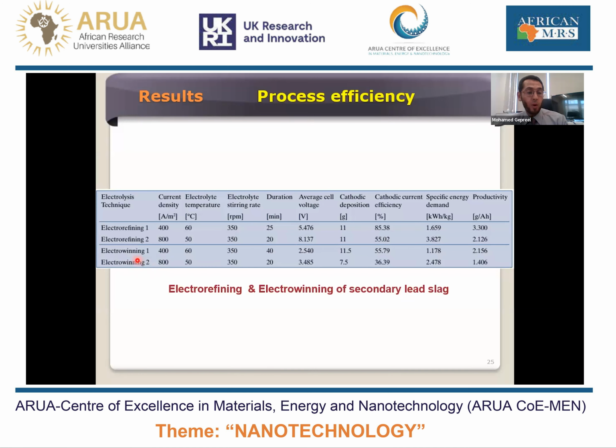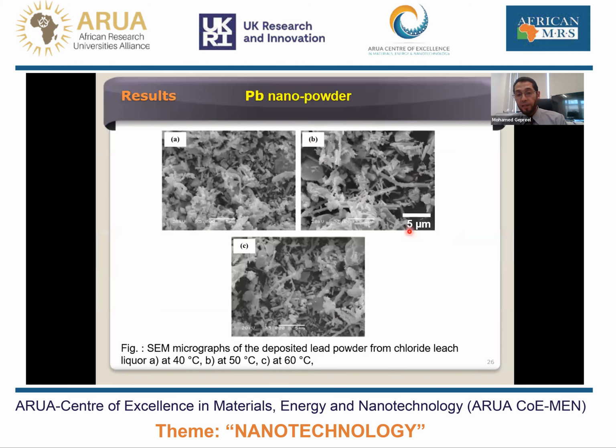Actually, electrowinning is a one-step process and electrorefining is a two-step process, which means cost. But at the end, the efficiency of the one-step process is less than that of the two-step process, so this should be optimized. At the end, we have fine lead powders, as we can see here. This is one of the selected conditions showing the effect of temperature on lead powder production. We can also see an irregular shape of lead particles. We can have rods, nanorods, fine powders, chunks, agglomerates, and so on.